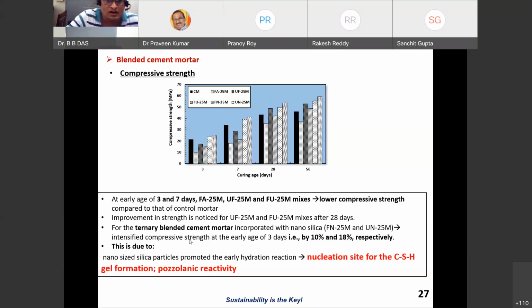Now come to the ternary blended mortar. Particularly with the nanoparticles, in the fly ash nanoparticles and ultrafine fly ash nanoparticles mixes, you can see here, even at 3 and 7 days, the compressive strength at the early age, at 3 days only, increased by 10% and 18% respectively. So that is the beauty of adding even a very small percentage of nanoparticles.